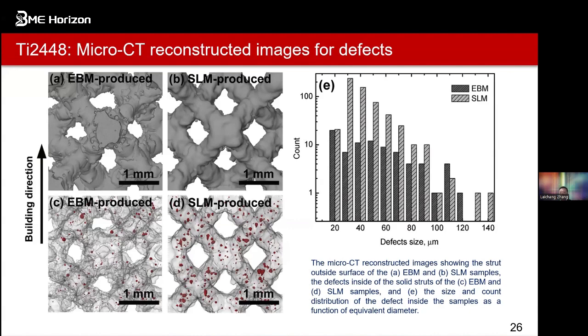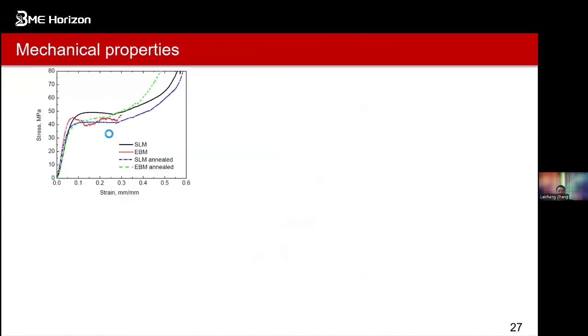And also you can see SLM still has a lot of big pores that are produced. So that's why a lot of them produce good mechanical properties. So of course we can see the structure. From the static properties it is quite good. You can see this one after homogenization still has no breaking, just shattering of the parts. That's because the structures can be deformed gradually. So that's what it means: these parts have a good tolerance.